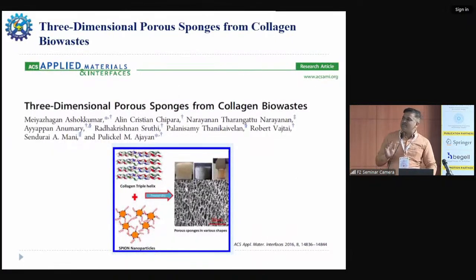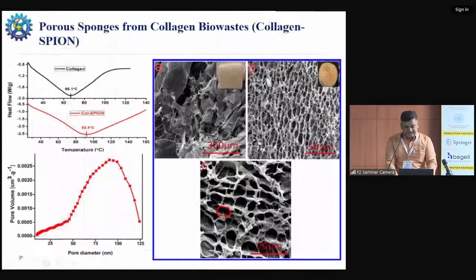So this is an example where we tried to convert this collagen waste into a porous spongy material, which is again highly magnetic. Here we use the superparamagnetic iron oxide nanoparticle, treat it with the collagen, and subject it to the freeze drying technique. Then we are able to convert it into a very nice spongy material. The sponge has very nice porosity, and therefore very good enhanced thermal stability and enhanced porosity.